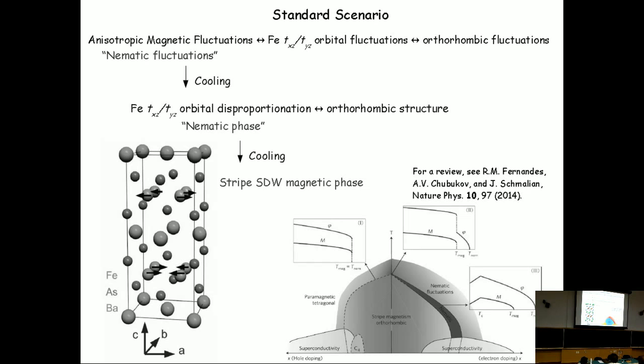And then on cooling, finally, we have some transition which coincides with the orthorhombic structural phase transition, where we finally have a long-range orbital disproportionation that we call this nematic phase. And sometimes at different temperatures on further cooling, we have this stripe SDW, spin density wave, magnetic phase in this system. So that's the standard scenario to describe the system, where the electronic and the structural transitions are the same, and the magnetic transition may be at a different temperature depending on doping.